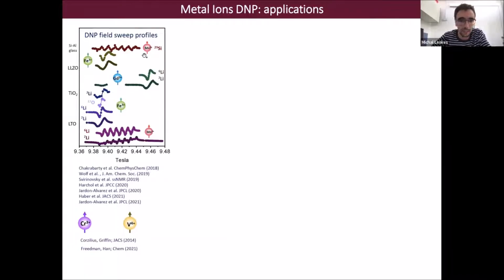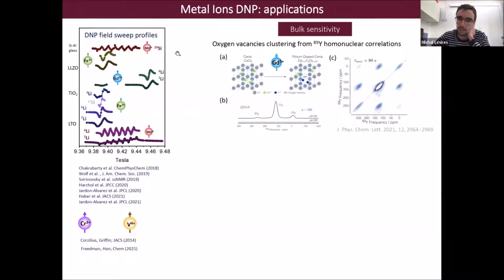And with that, we were able to get large enhancement on a series of different nuclei. I want to show you two short examples of the type of research questions that we try to address with this approach. So for example, in this study here, we looked at this yttrium-doped ceria, which is an oxygen ion conductor, and therefore it's used as solid electrolyte in fuel cells. And we doped this material with gadolinium 3+.